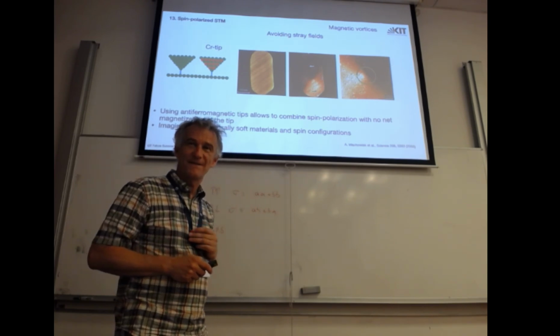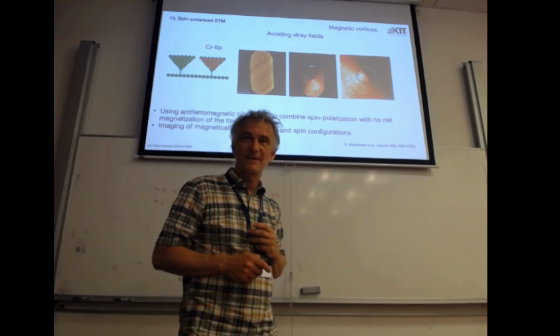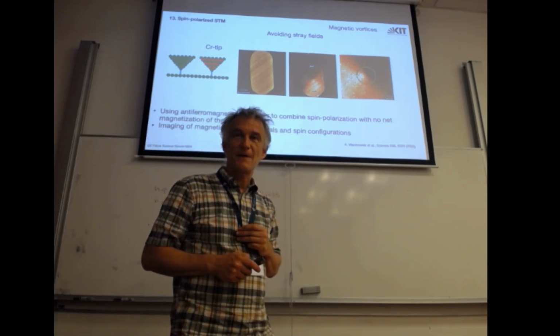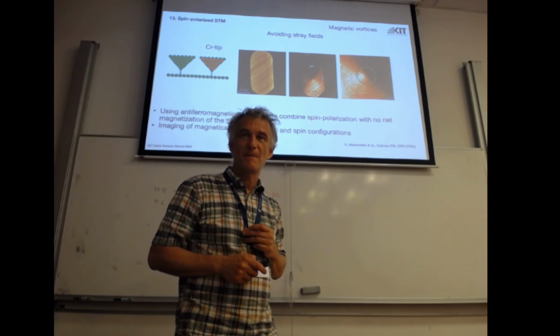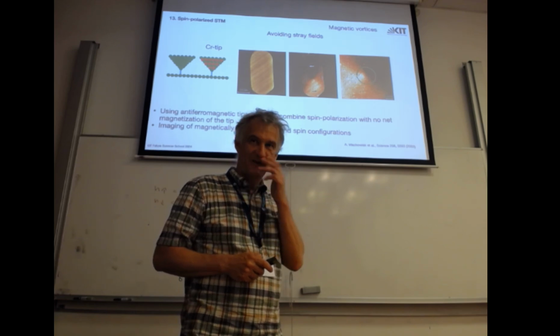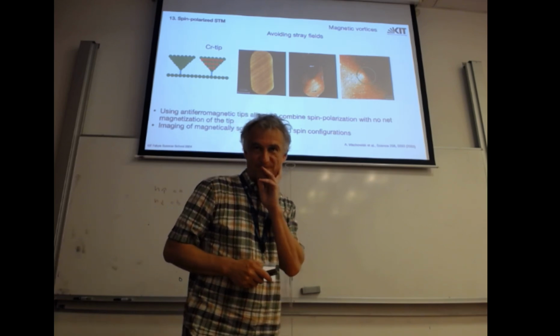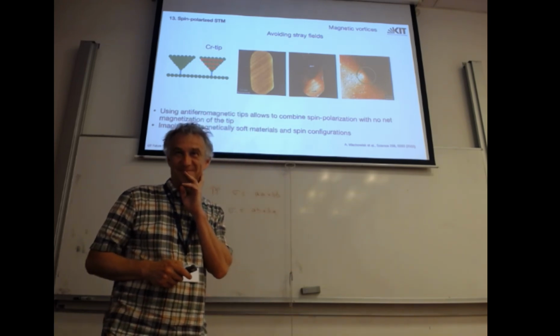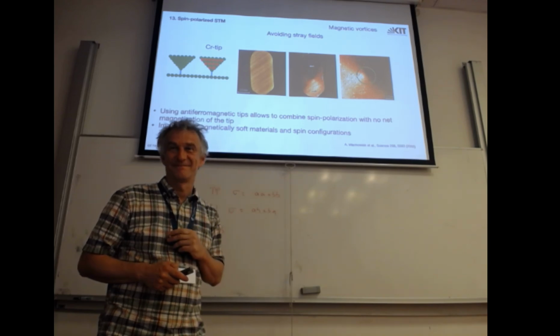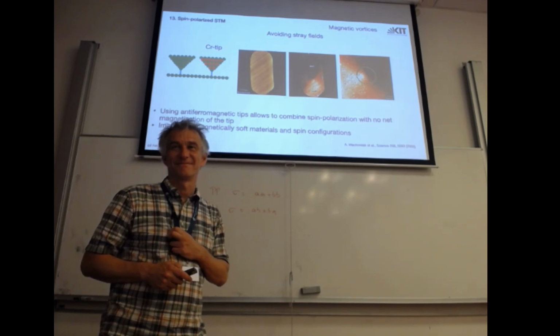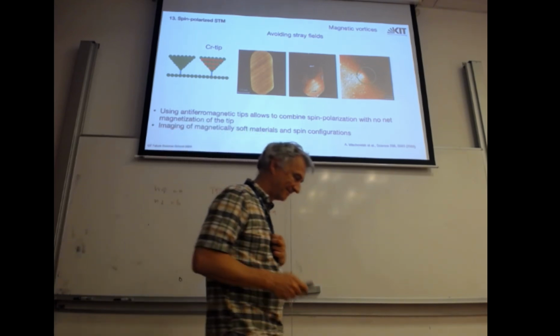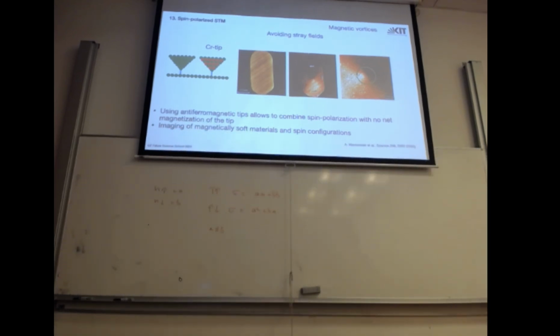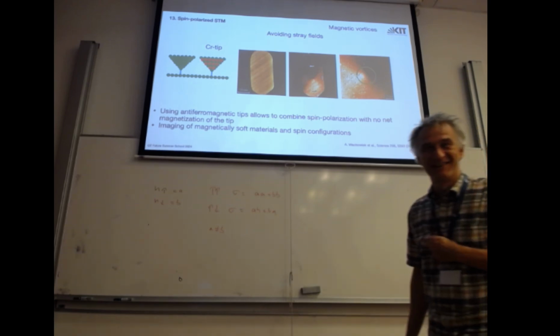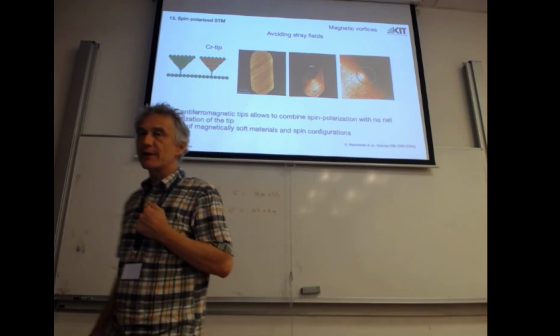Maybe I don't understand something, but we can imagine a situation where I have a non-magnetic material with a long spin relaxation time, and first I inject, somehow, spin polarized electrons, and then I bring this tip, which is non-magnetic, so no problems with magnetization whatsoever, to my sample. Well, to put the tip takes half an hour. I don't think there are spin lifetimes in your samples of half an hour. So I can polarize. There are experiments actually like this.